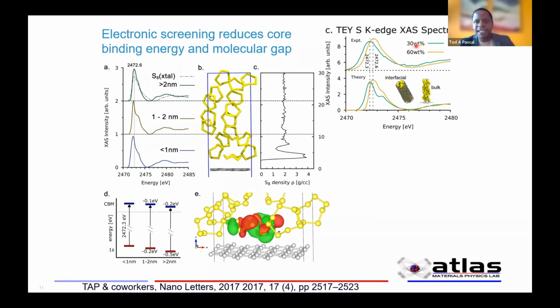Yeah, so we do it in terms of the weight percent of sulfur. So 30 weight percent sulfur basically fills the pores. And that just has to do with, on average, the size of your pores and how much actual space, because the pores fill first. That's the bottom line that we figured out. The pores fill first, and then once the pores are filled, we start getting filling of the internal. So this 30 weight percent would represent enough sulfur to fill all of the pores in this case.